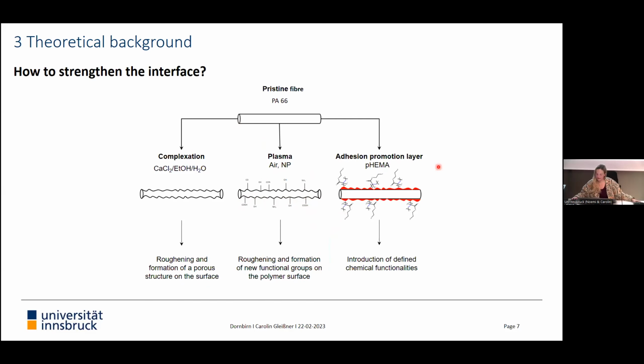In the third technique, these are all degradative techniques, but in the third technique, I wanted to introduce an adhesion promotion layer on the polymer. So the advantage of this technique is that you introduce defined chemical functionalities on the surface via defined chemical reactions. In my case, I tried to do a grafting with 2-hydroxyethyl methacrylate, so short HEMA. And I grafted it, or did a polymerization, so that in the end I had a polyHEMA layer on my substrate. And of course, the topography also changes.